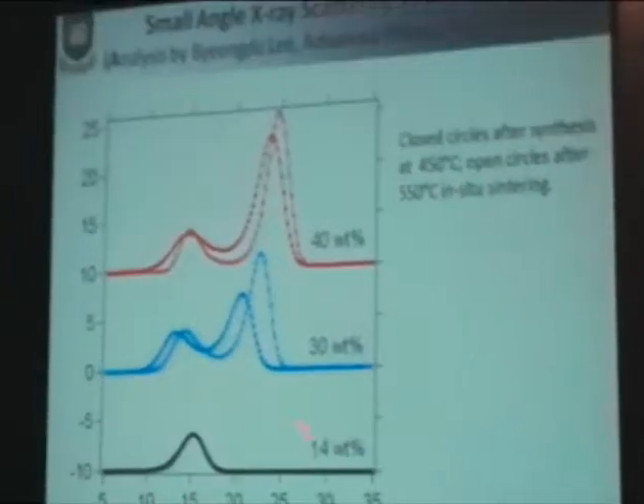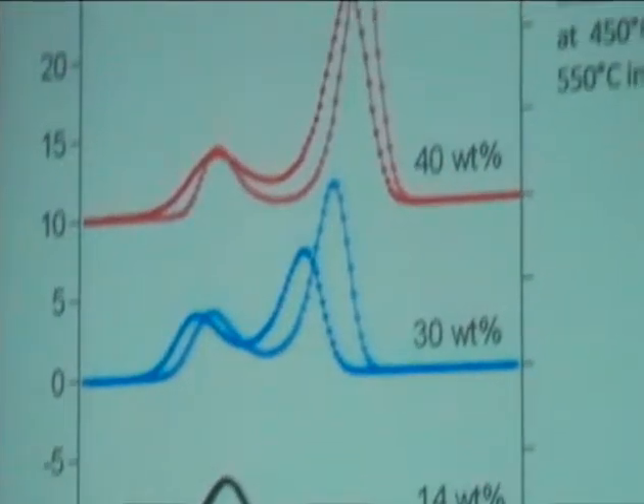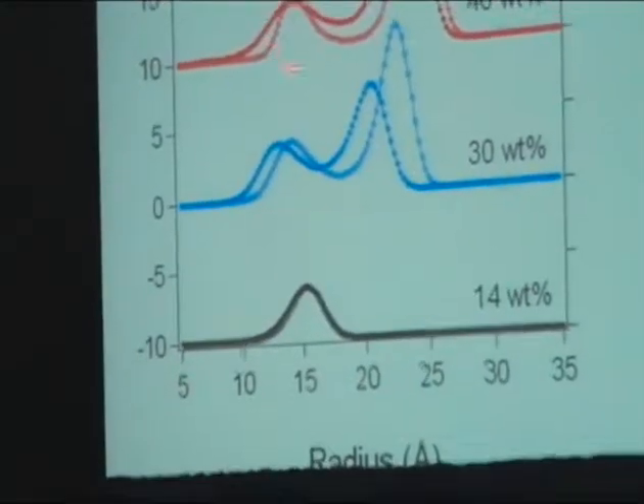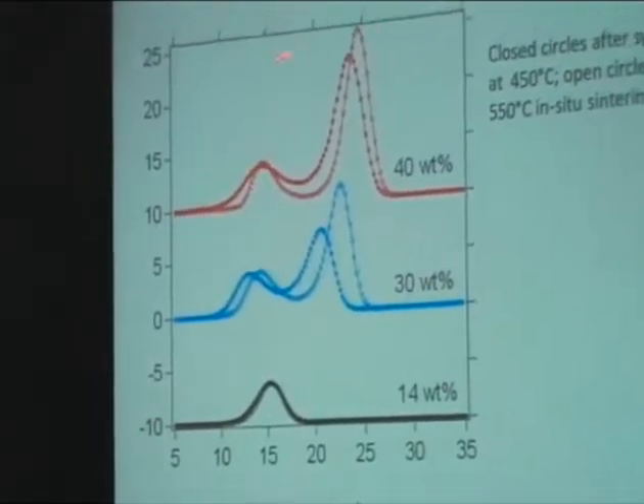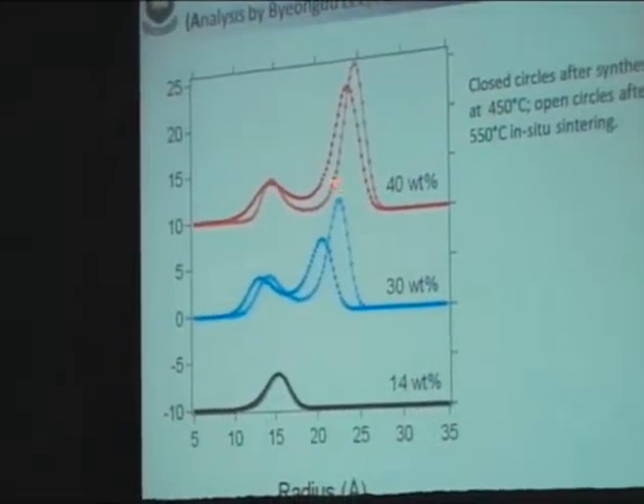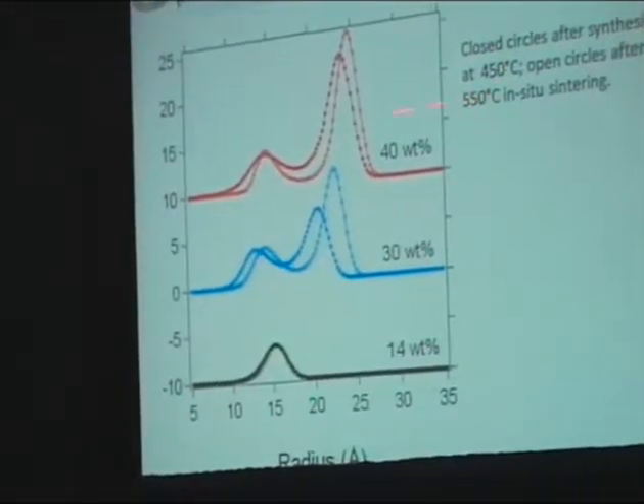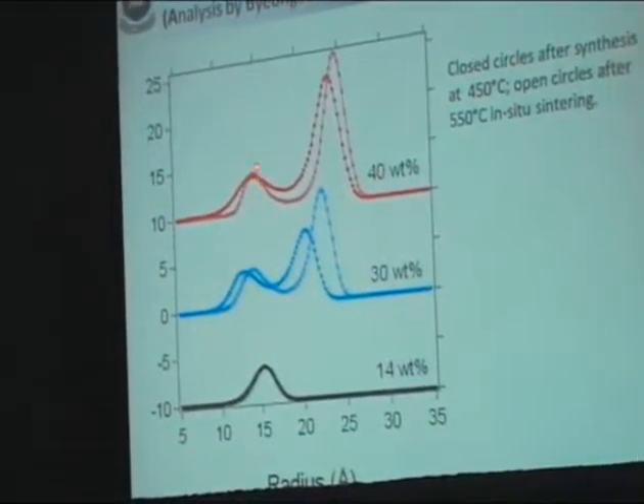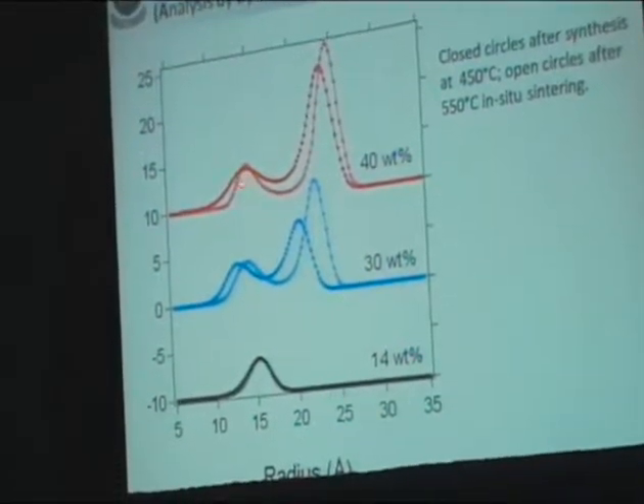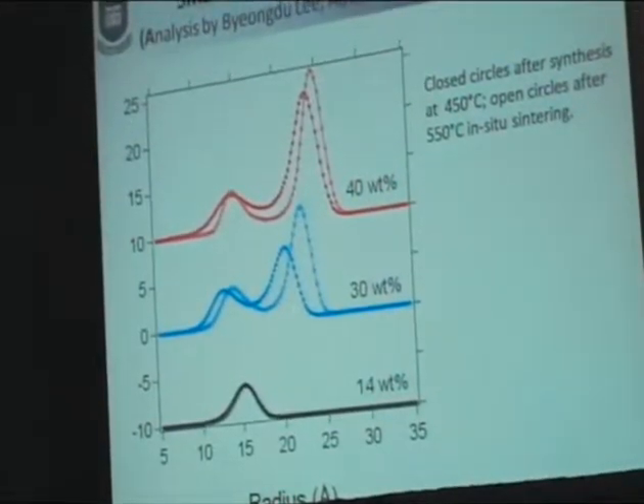By using small angle scattering, we can show that we have a bimodal distribution. At low loadings, it's a single distribution, and then in situ, we're able to go from the synthesis temperature up to 550 and show that they're stable. But at high loadings, you have this bimodal distribution of something down here in the order of a couple of nanometers and something that's closer to 10 nanometers. Even with a modest increase of sintering from 450 to 550, the smaller particles are stable, but the large ones continue to sinter.